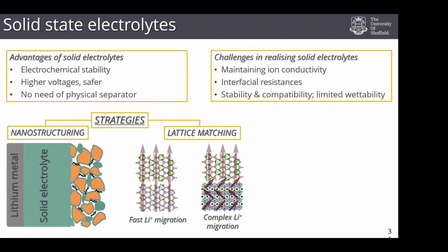The other thing we're doing is designing our cathodes and our electrolytes to have very similar crystal structures. If they look very similar, then when we click them together almost like Lego, they might fit quite nicely, and then we might be able to get lithium transporting across that interface.